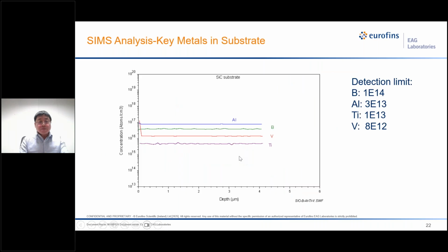SIMS can also measure different elements, metals in the substrate. Here it shows the result from SIMS, and we can get analysis of boron, aluminum, vanadium, titanium.